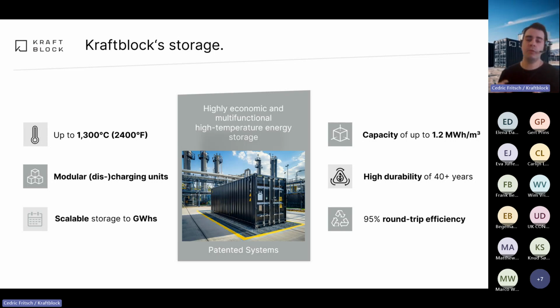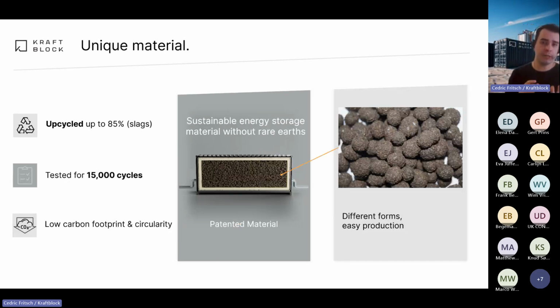And our material, we took a bit of a different route. We looked first for the material, and we found it in steel slags, which is a waste product. Thus, the material is pretty cheap. We mill it down, add some additional material that improves the heat distribution and heat conductivity, for example, and then we mix it together with an organic binder to make these pellets, but also in different forms like blocks, which are used in certain use cases. And this really has a low carbon footprint as it uses waste products. So this is a nice circular economy.